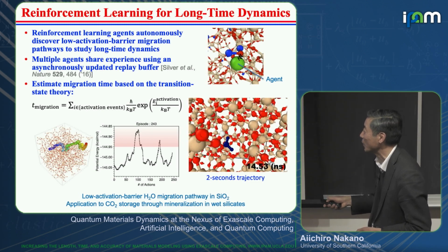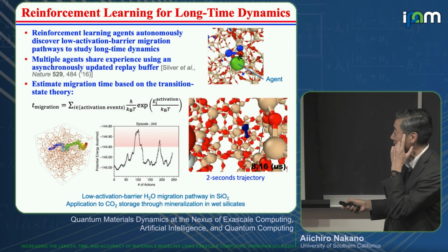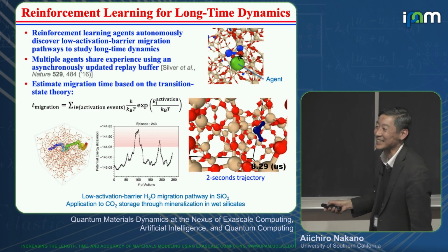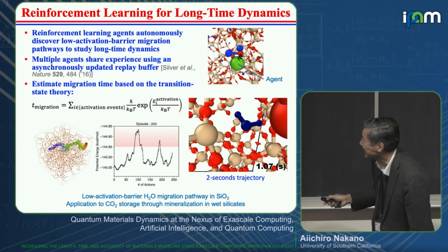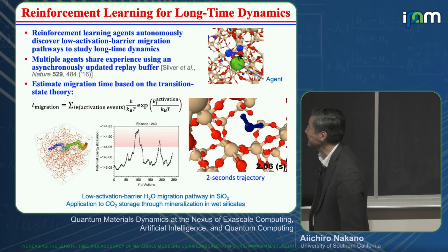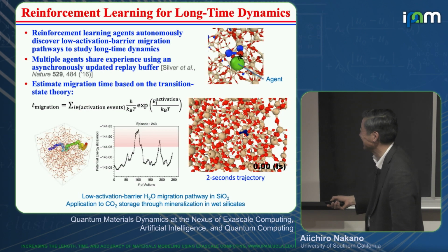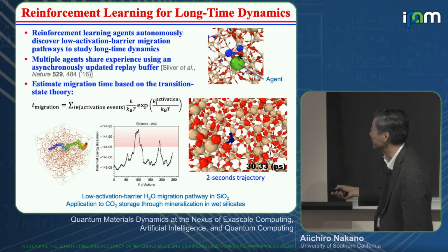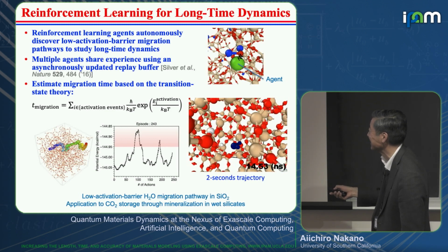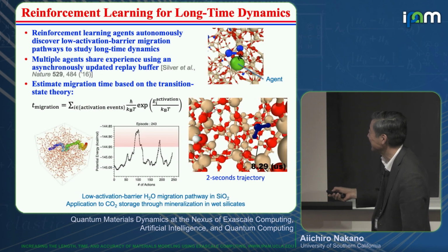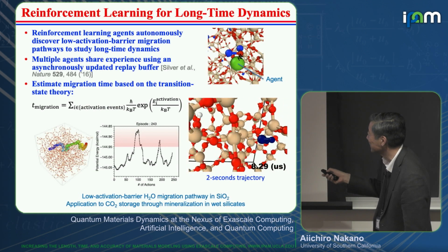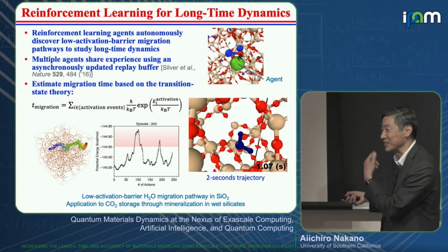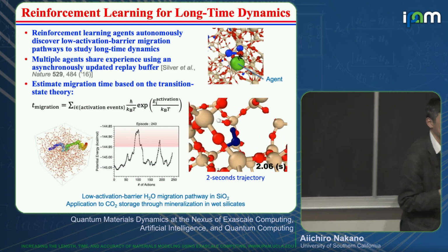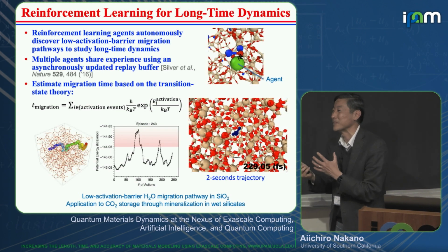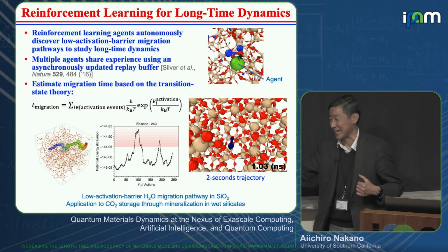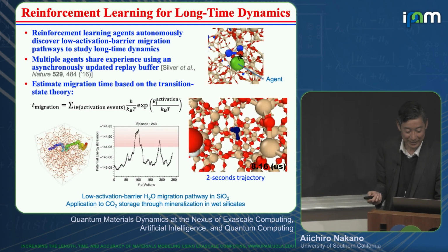And this is the energy profile along the path, from which we can compute the time. And this is the 2-second trajectory. We cannot do that with molecular dynamics. So you can see, the agent finds a very non-trivial path. This is just the start, 20 seconds, 30 picoseconds, 1 nanosecond, 14 nanoseconds, microsecond. I think there's a very high barrier it crossed. It was impossible to find this. Right now we try to serialize this so we can do some non-equilibrium statistical mechanics. Right now we're just finding a path, but we see a lot of potential.